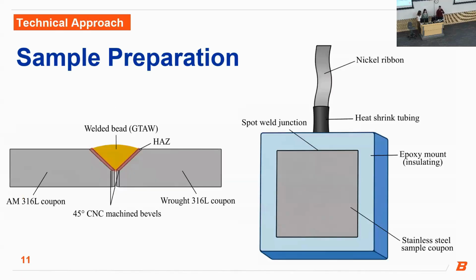Okay, to accomplish our goals, we first needed to prepare our samples. The schematic on the right shows how our samples looked after they were prepared. Each sample had a nickel ribbon spot welded to them with heat shrink tubing covering at least half of the ribbon to protect it from the saltwater solution. The nickel ribbon was needed to make an electrical connection. Then the samples were mounted in epoxy to prevent galvanic corrosion between the nickel ribbon and the stainless steel.